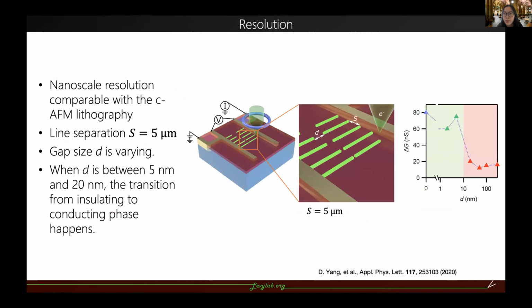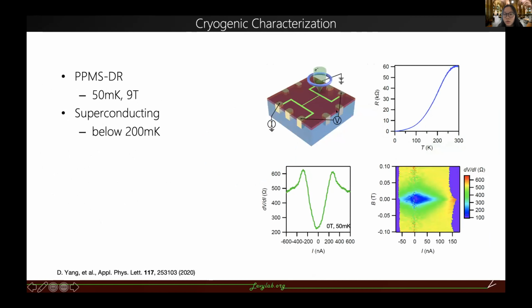And it's natural to ask what the resolution of this writing process is, once we have a way to write the devices. To explore that, I made a bunch of nanowires separated by 5 micrometers, a distance large enough to suppress crosstalk between nanowires. I have a gap in the middle of the nanowire, and I'm varying the gap size. As the gap gets smaller and smaller, at some point the gap will be covered by the resolution. We found the resolution of the writing is at around the sub-10 nanometer scale, which is comparable with conductive AFM lithography. We also did some transport measurements on the devices we created, and we observed superconducting behavior below 200 millikelvin, which is consistent with other LAO-STO reports.